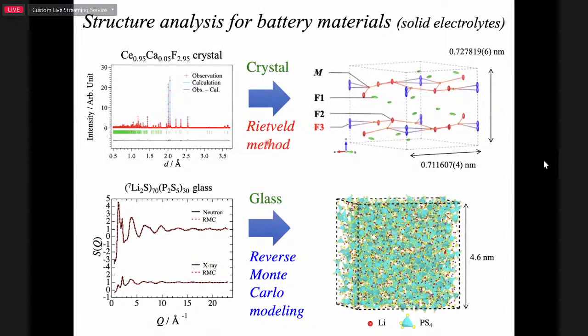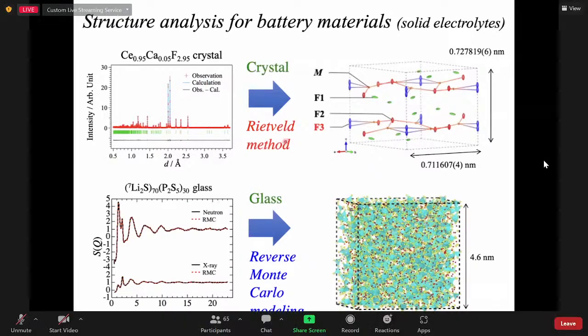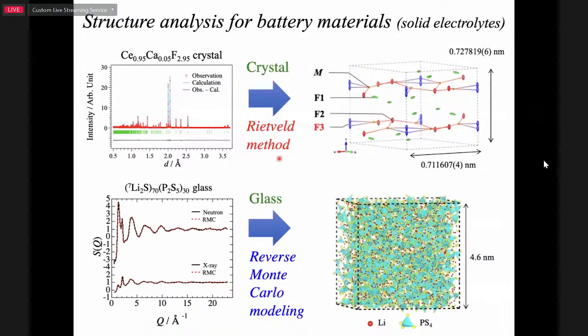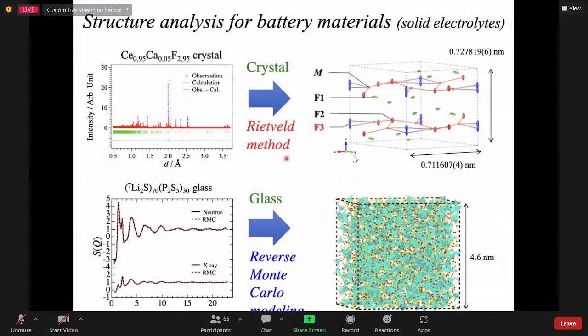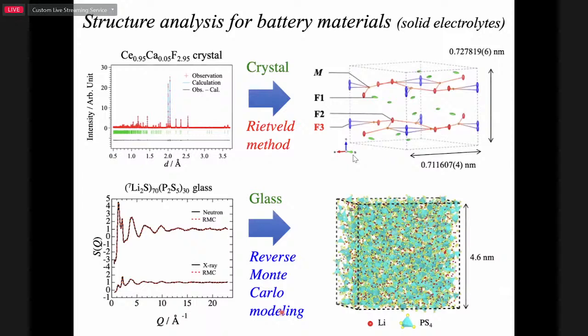Okay, so after collecting the neutron diffraction data, we try to determine the crystal structure or amorphous structure of the material. This picture shows the neutron diffraction data for calcium-doped cerium fluoride crystal, and this is Li2S-P2S5 glass, respectively. In the case of crystalline materials, the Rietveld method is very common to refine the crystal structure. On the other hand, reverse Monte Carlo modeling is very popular to visualize the three-dimensional structure of amorphous and liquid materials like this. So both methods are very interesting.